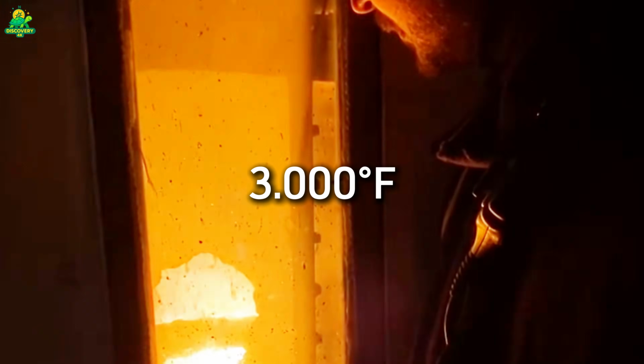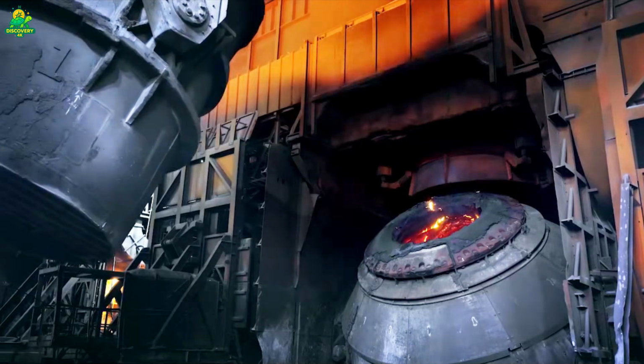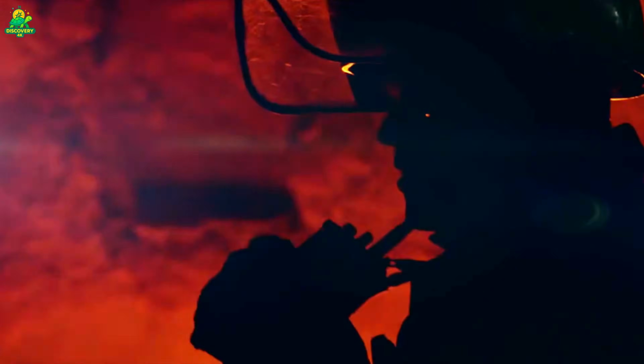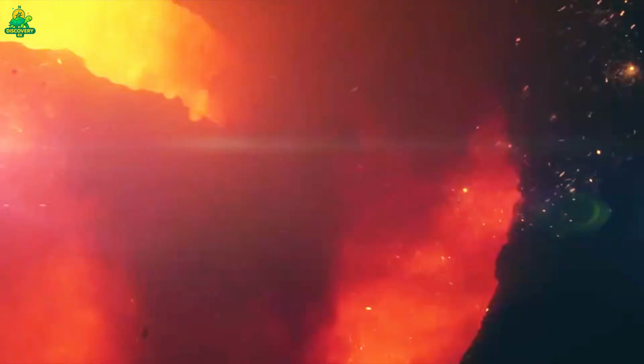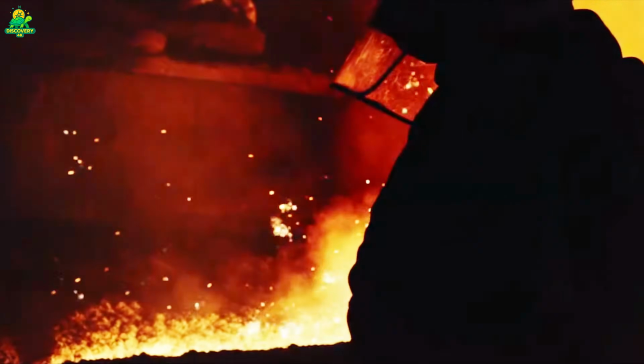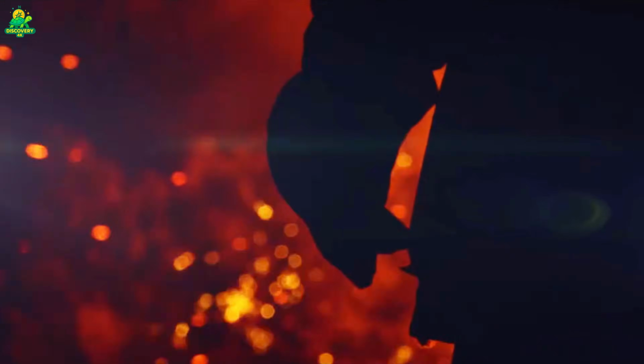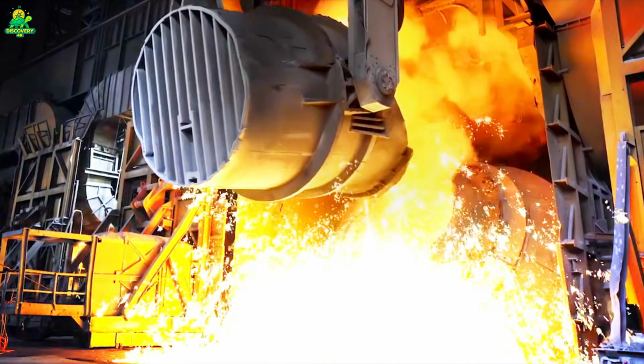Inside, electricity arcs across carbon electrodes, reaching temperatures above 3,000 degrees Fahrenheit. The scrap melts into a glowing river of liquid steel. Chemical engineers constantly test samples, adjusting the recipe with carbon, manganese, and silicon to achieve the exact properties needed for rod steel: strong, flexible, and consistent.